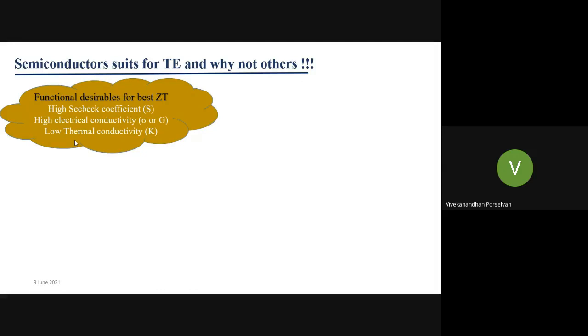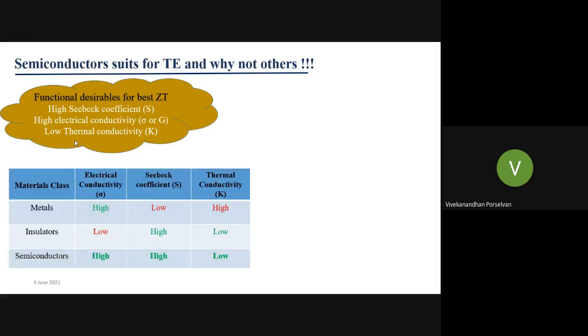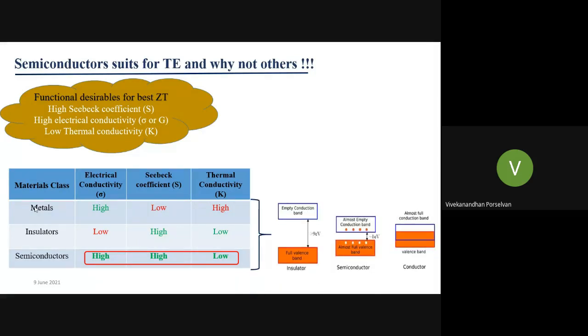So why are semiconductors suited for thermoelectric generators, and why not others? As heard, the functional desirables for the best ZT are a higher Seebeck effect, higher electrical conductivity, and low thermal conductivity. If you look at metals, the electrical conductivity is very high, the Seebeck coefficient is very low, and the thermal conductivity is quite high. Insulators have lower electrical conductivity, higher Seebeck coefficient, and low thermal conductivity. Talking about semiconductors, the electrical conductivity and Seebeck coefficient are both high, thereby giving a higher power factor with lower thermal conductivity. These are the desirables in contrast to the thermoelectric need. This can be attributed to the band structure phenomena associated with the materials.